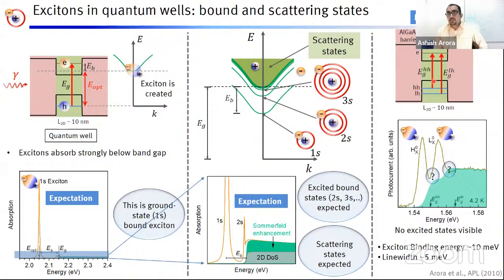So there are two types of excitons called heavy hole and light hole excitons, and they appear as strong resonances now in the absorption spectrum. Now this is experiment, and then there are these step-like features which are superimposed on top of each other, one due to heavy hole and one due to light hole, and then they contribute to the absorption spectrum with the Sommerfeld enhanced 2D step-like feature.